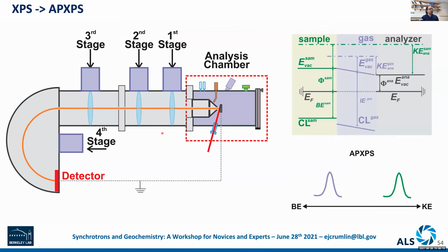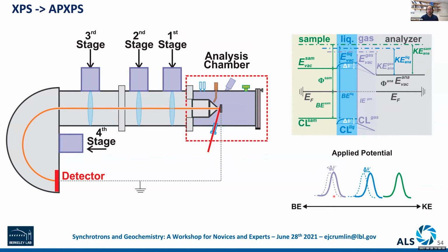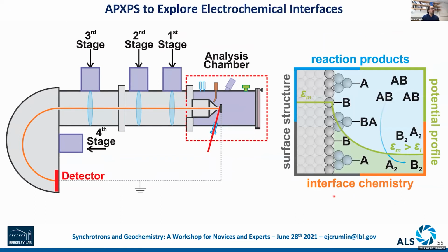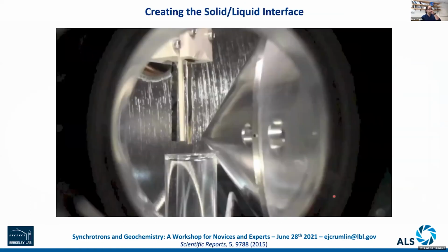So if we go from soft X-ray to tender X-rays, this now allows us to even start having these condensed phases. So for example, liquids. And if we can operate at 20 torr pressures, 20 torr is a great pressure because at room temperature, water is in the liquid vapor phase. So we can actually start looking at solid liquid interfaces as well. So this allows us to look at solid liquid gas interface all simultaneously. If you can form a solid liquid interface, we can even start applying potentials and look at how these potential changes are taking place.